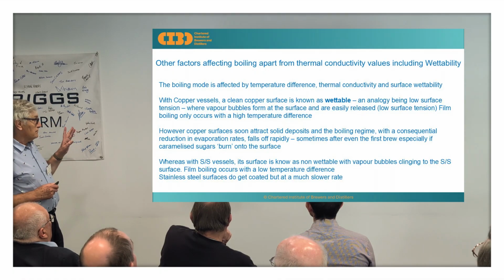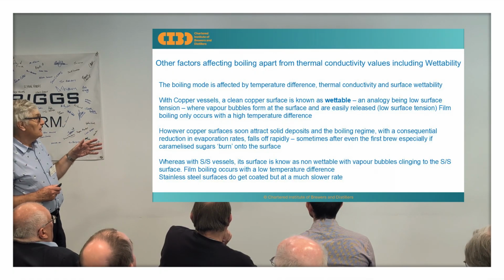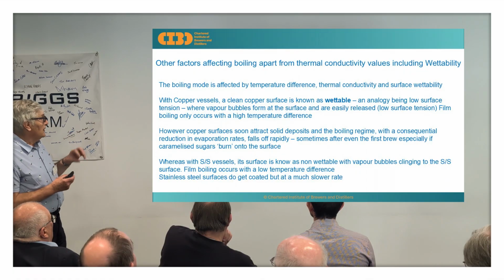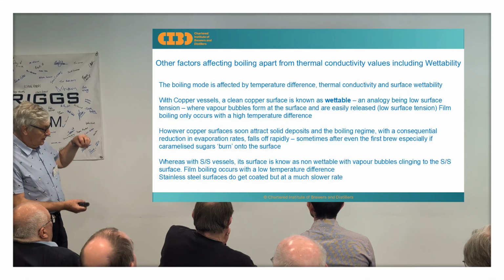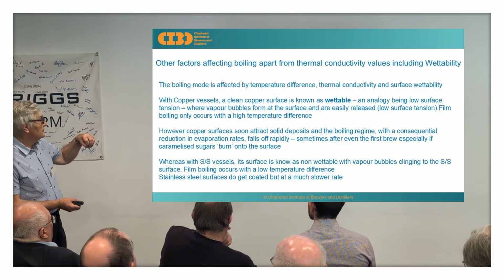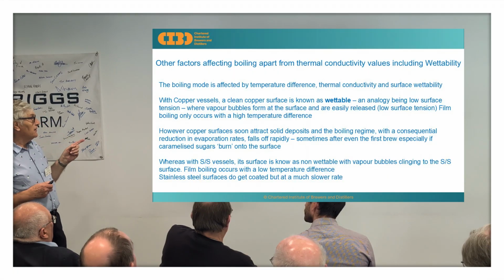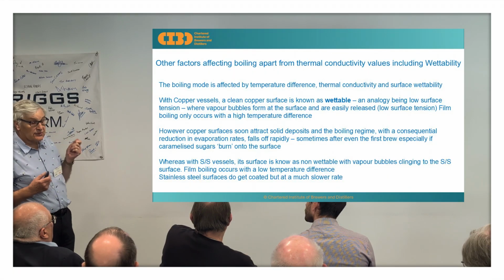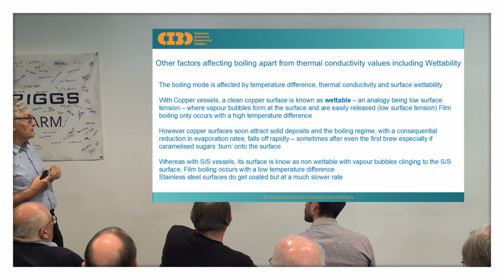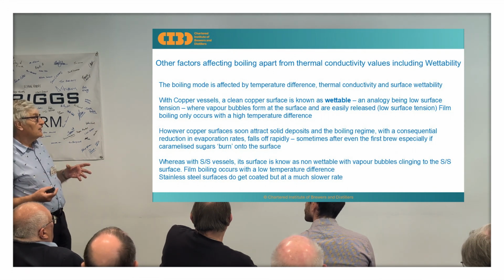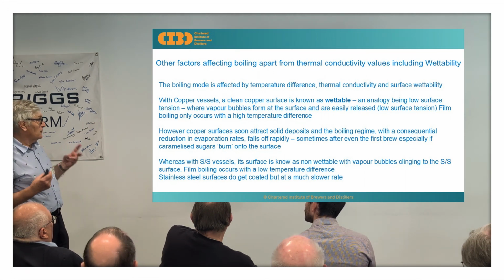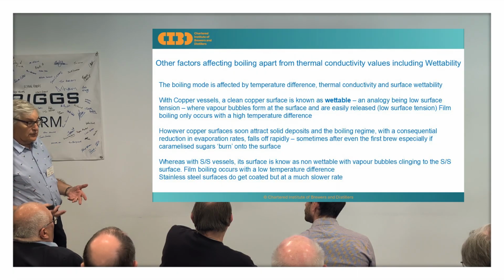Where, as I say, they're easily released, and the film boiling only occurs with a high delta T, high temperature difference. Problem is with copper that these surfaces soon attract solid deposits, and the boiling regime with a consequential reduction in evaporation, it falls off.